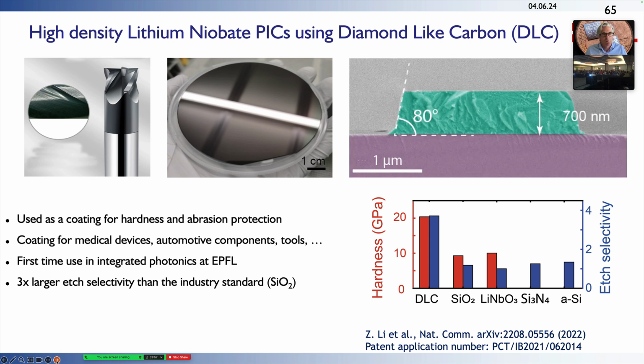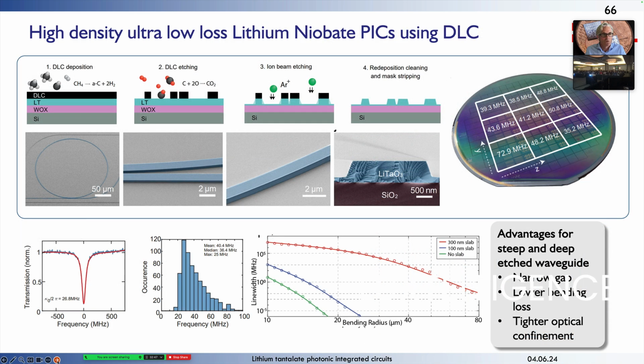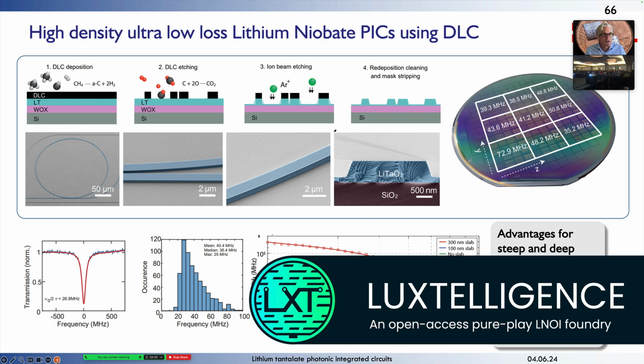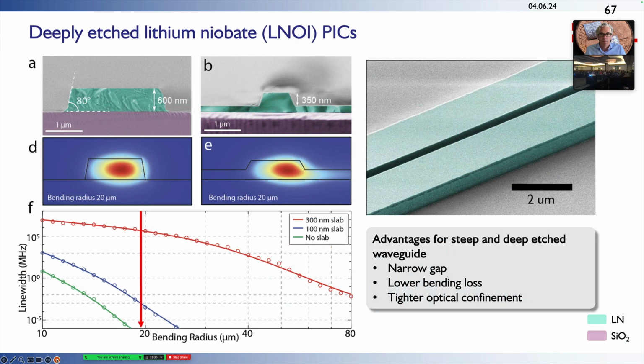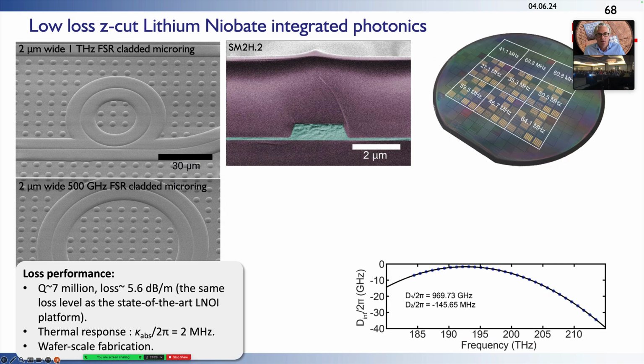And using this material, we're able now to generate deeply etched lithium niobate, lithium tantalate waveguides that have losses that are less than 10 dB per meter. So they're also fairly low loss compared to what could be done just a few years ago. And so we've commercialized this with an open access foundry called Luxtelligence. And we can now generate deeply etched waveguides with loss levels well below 10 dB per meter, while keeping actually very tight bend radius. And what can you do with these materials?